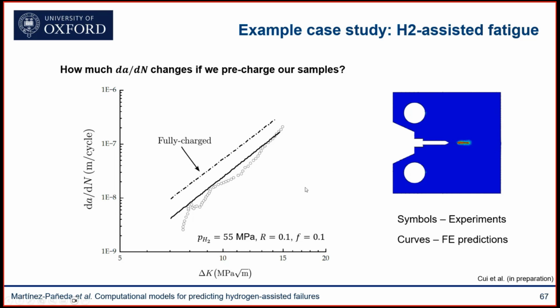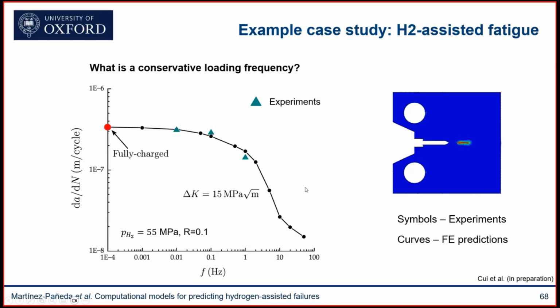Another aspect that we can do is the role of frequency. I mentioned before, the experiments are typically conducted at frequencies of 1 hertz because this is what is practically convenient. From time to time, there are experiments being conducted at lower frequencies, but this is very expensive. And also, they're a bit afraid that maybe they'll have some leaks at this very low frequency. It's quite challenging to do experiments at low frequencies. So what we can do with our model is we can do virtual experiments at a wide range of frequencies.